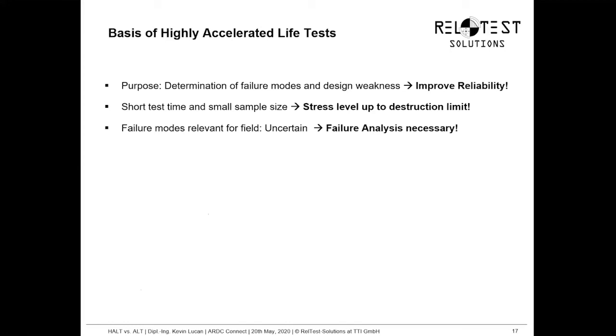But on the other hand, we have to go so high with our stress that we reach the destruction limit. And this can be critical, because going that high with our stress level, we have to think about whether the failure we are seeing in a highly accelerated life test is relevant for field load conditions or not. So a failure analysis is necessary.